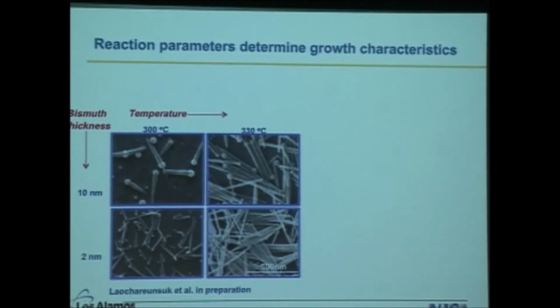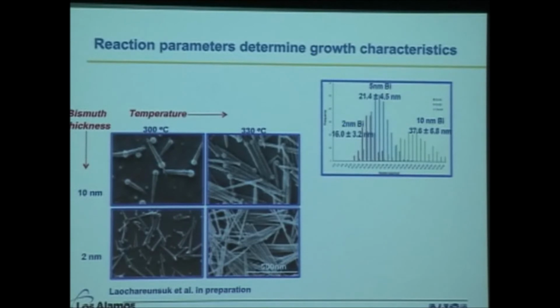And so initially we just did some basic studies on the growth processes as a function of temperature, as a function in this case of bismuth film thickness. In this case we were not putting in individual particles on a substrate. We actually supplied a film of bismuth that melted under the growth conditions and formed droplets on the substrate. So fairly random, but it was the easiest way to go. And so as a function of bismuth thickness, you can clearly see an effect on the diameter of the particles or of the wires formed.